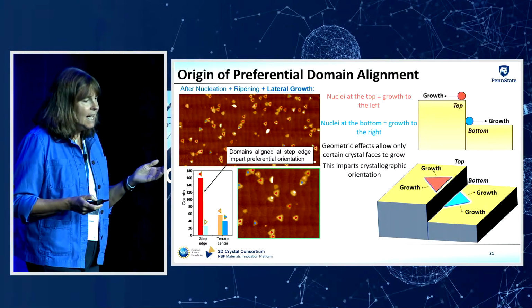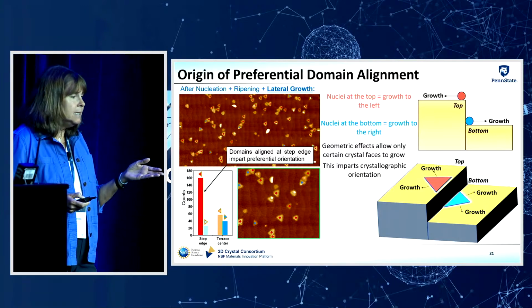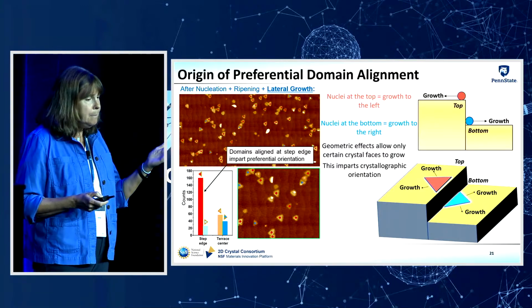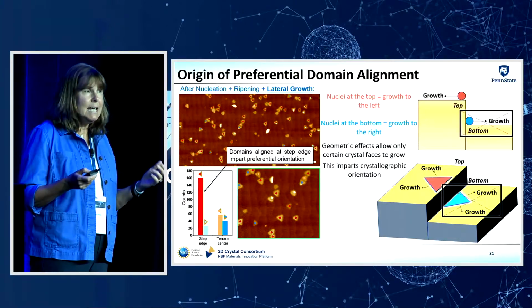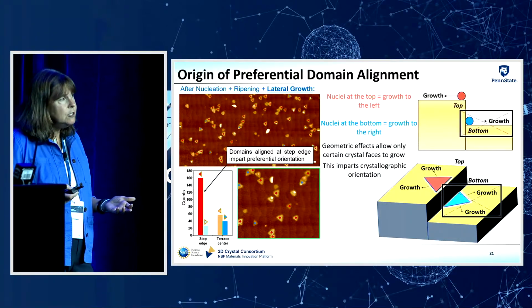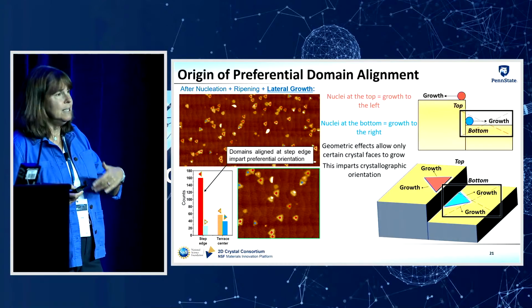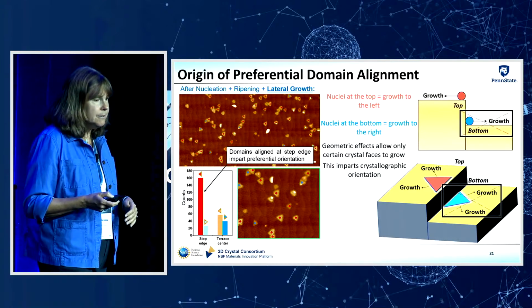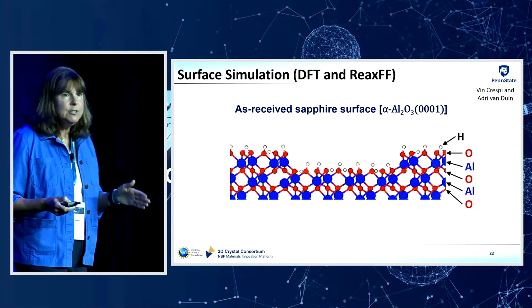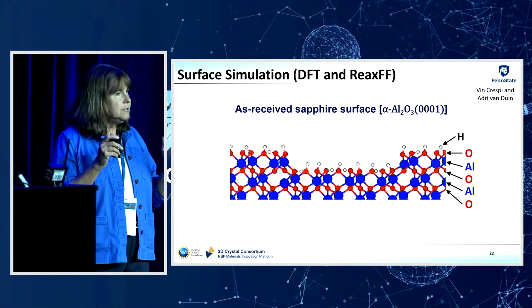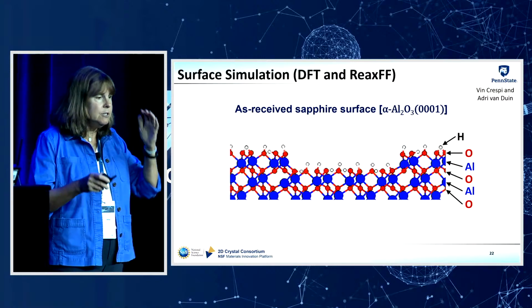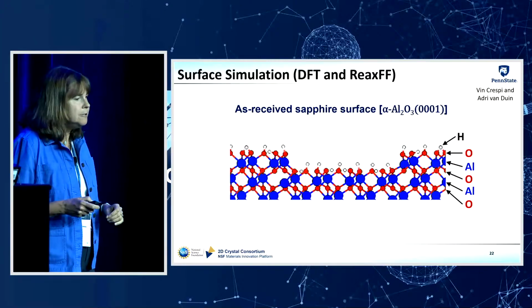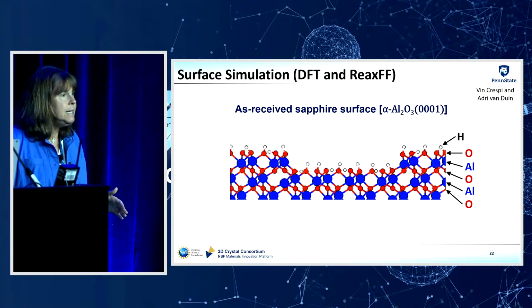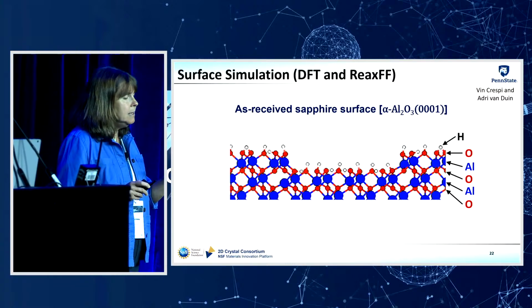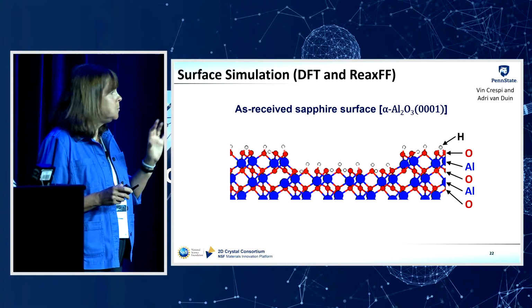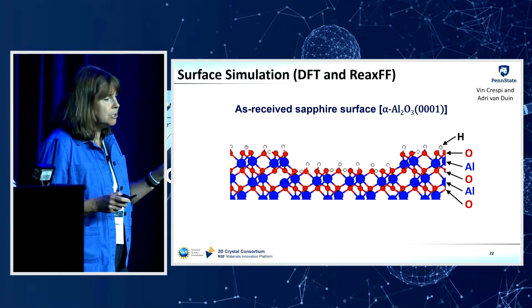Now, the question that we had is, what we see experimentally is that the domains are nucleating at the top edge of the step. They're not nucleating at the bottom edge of the step, which is the location that you would expect them to based on a general Ehrlich-Schwoebel barrier type of model. So we wanted to understand this more, and we reached out to our theory colleagues in the 2D Crystal Consortium, Vin Crespi and Adri van Duin, and they did some DFT calculations to take a look at the location on the sapphire surface where we might expect nucleation to occur.